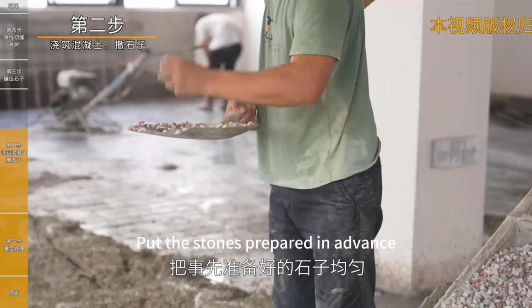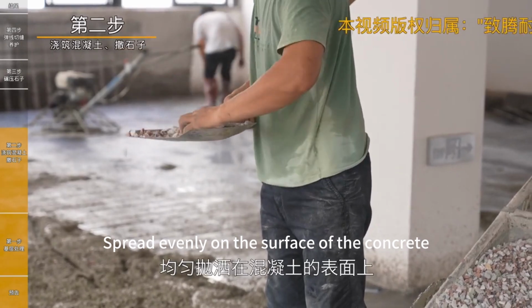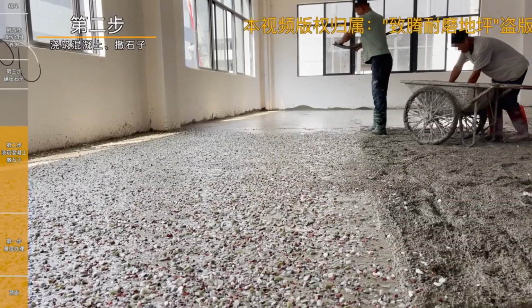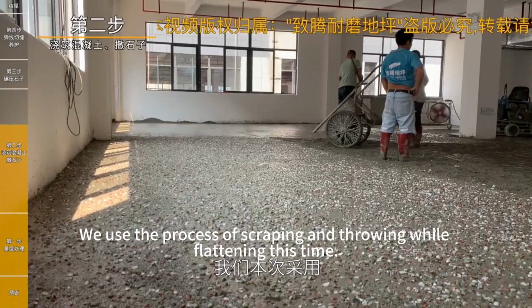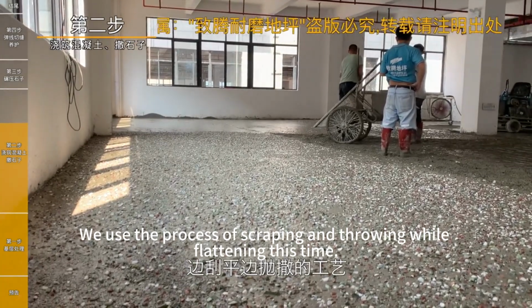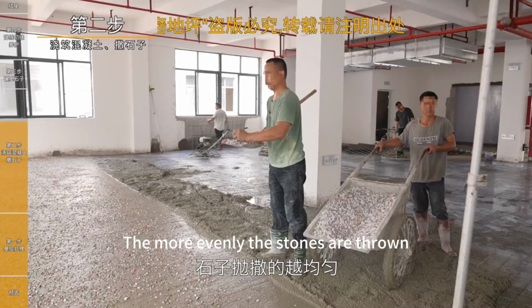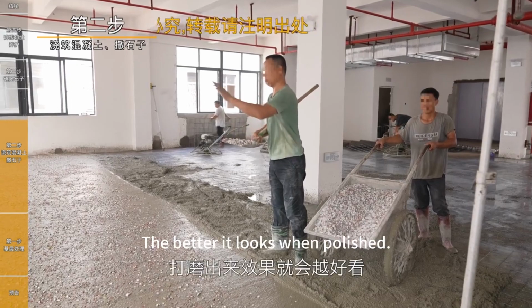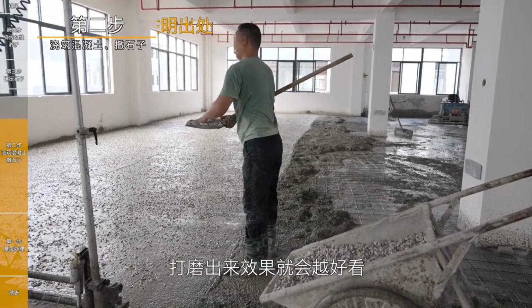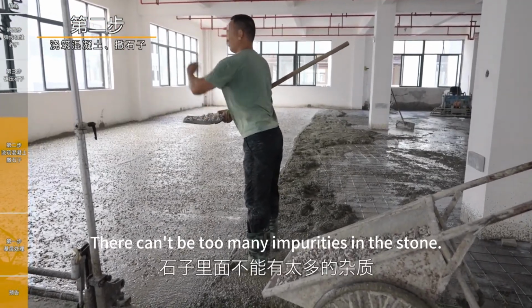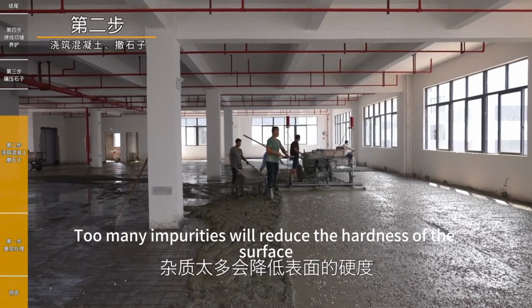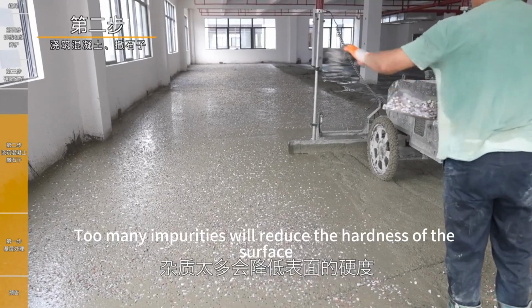Put the stones prepared in advance and spread them evenly on the surface of the concrete. We use the process of scraping and throwing while flattening this time. The more evenly the stones are thrown, the better it looks when polished. There can't be too many impurities in the stone. Too many impurities will reduce the hardness of the surface.